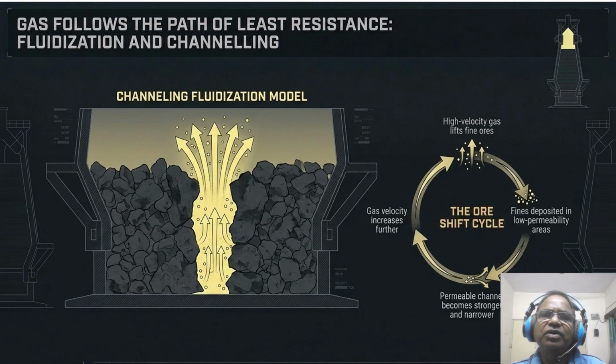The gas is not staying in contact with the ore long enough for efficient reduction. You will see your CO-CO2 ratio tank and your top temperature spike because the heat is not being transferred to the burden. This is not just a waste of energy. It's a sign of a physical slip that can damage your top gear.